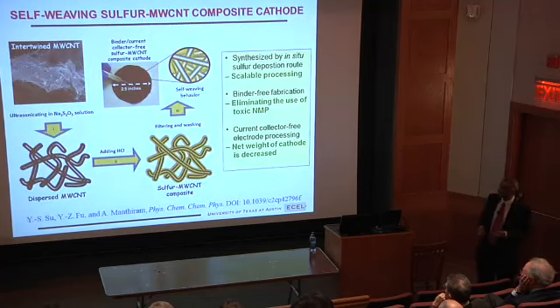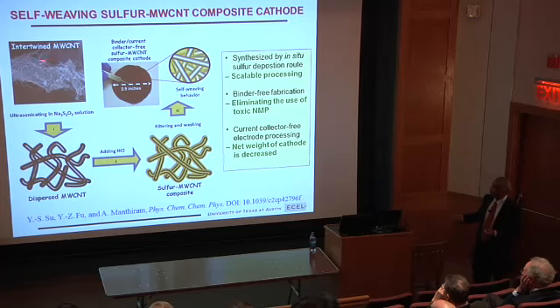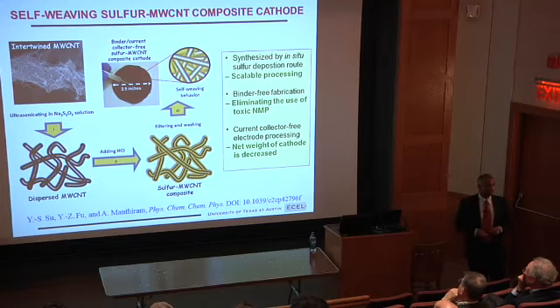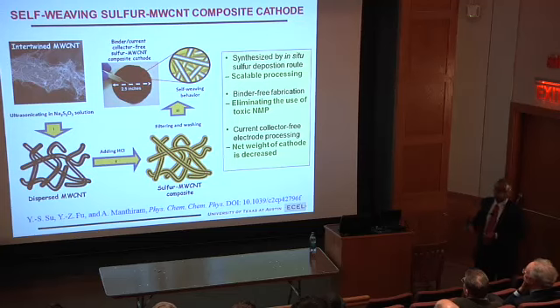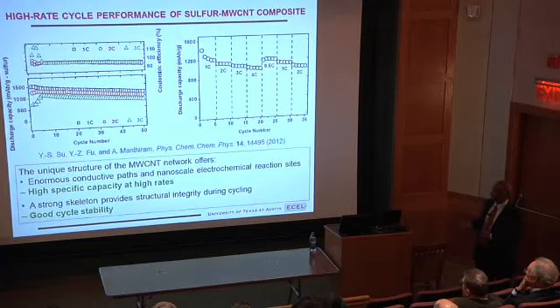So all these problems. So we have been following a few strategies. One is to have a multi-wall carbon nanotube, disperse it in sodium thiosulfate, then you add hydrochloric acid, that's a high school reaction. You will generate sulfur in the multi-wall carbon nanotube. We can actually peel it off. No binder, no NMP solvent, N-methyl pyrrolidone, a toxic solvent. It's highly conductive. So you may be able to use it even without a current collector. So that's a lot of advantages. And that's the performance.